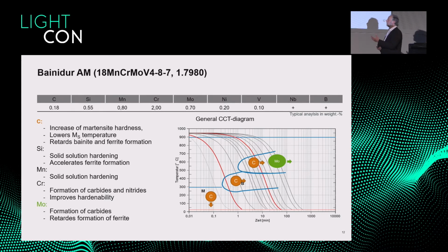And the idea of the bainitic steels is you have to heat up, deform, forge, you have to do it anyway, and then you cool down and do nothing, cool with the right cooling rate, and you get a bainitic structure. And bainite looks very similar to martensite and has nearly similar properties as a quenched and tempered martensite. To increase the range for the bainite transformation, you have to play with the chemical analysis, and this is done in this case with carbon. And to move the ferrite pearlite reaction to longer times, you have to add molybdenum. And if you reduce carbon, you have a softer structure than a hard martensite.